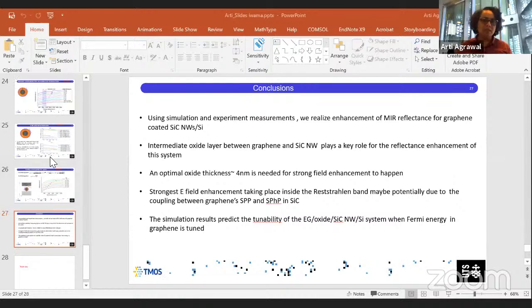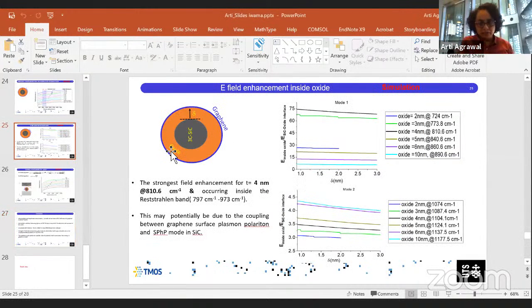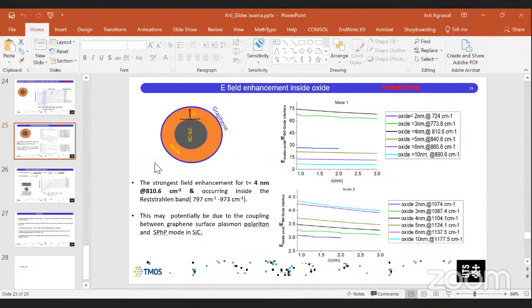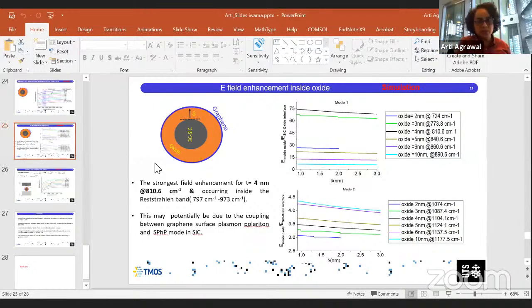Okay, so what we think about the mechanism is that typically in any structure, if the tail of the field of the plasmon and the tail of the field of the phonon are able to reach each other, then they can couple. That's what we expect. But we need to do some more experiments with S-SNOM to be able to actually look at the fields experimentally and verify this. Remember, these nanowires are very thin, really small, and quite complicated. So being able to look at the field inside a 2 nanometer region is not easy. That is one of the things that is currently being done.